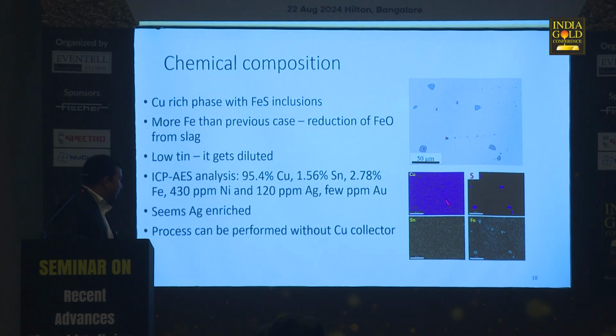So again, some microscopy, but essentially what we have is again copper tin. In this case, since we have used copper collectors, things get diluted. So you can see it shows only 1.56% tin. Since this was a small amount, we had to use copper because the mass contained a very small amount of metal, so it would have been difficult to separate. But in practice, if you have a large volume, you don't need to use the copper collector.